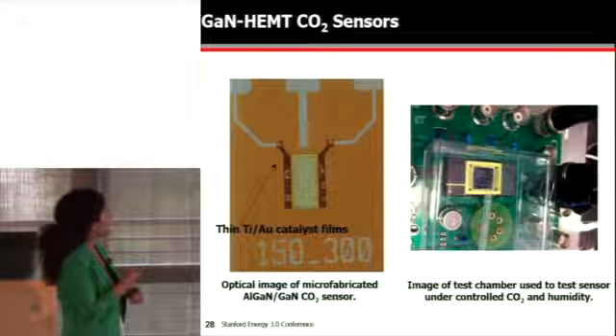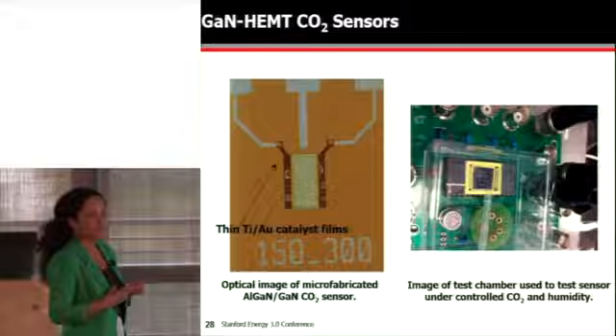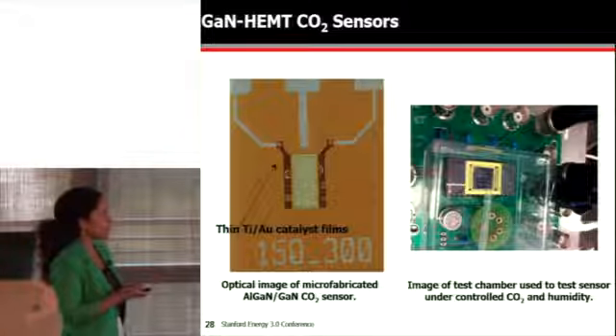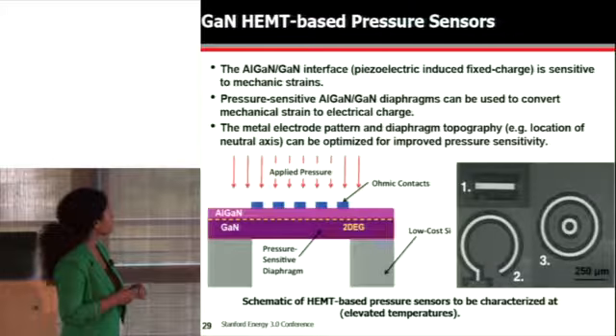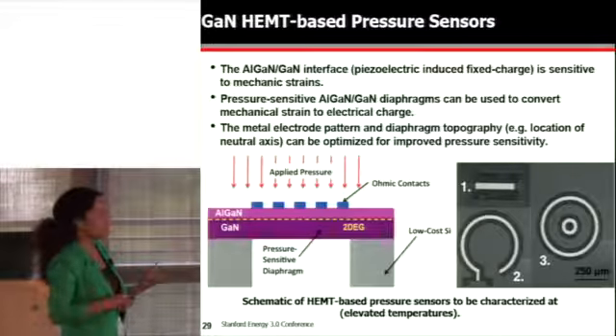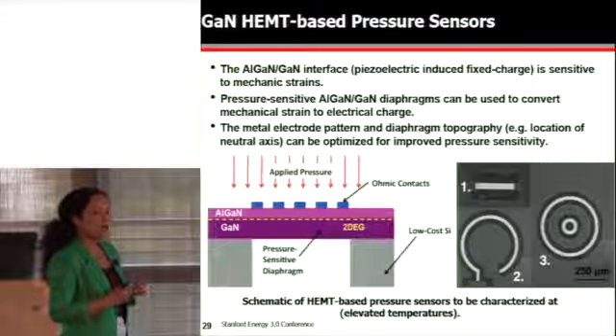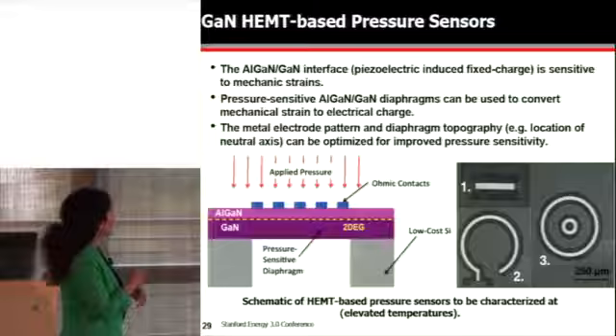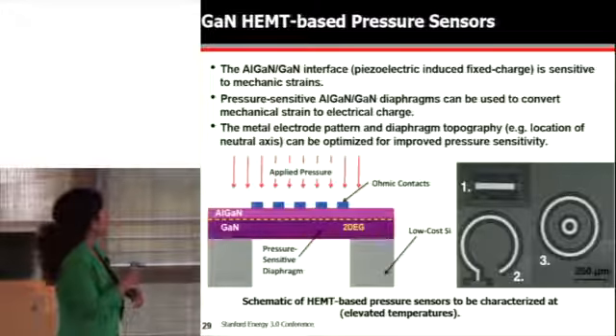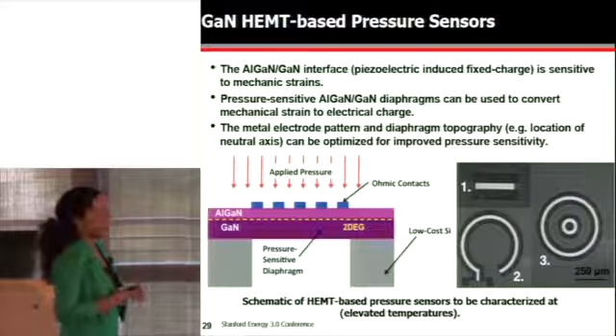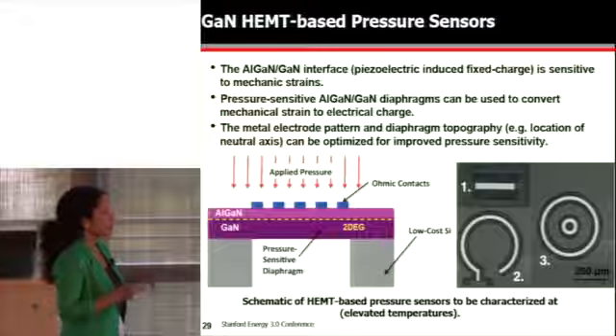And so the idea is that we can relate the concentration of CO2 to the IV characteristics of the sensor. In addition, we're creating high temperature pressure sensors. As I mentioned before, the gallium nitride is sensitive to applied strain. So if I create a diaphragm where I have applied pressure on top of it, the diaphragm will start to displace, and that will induce strain within the actual mechanical structure and change the strain profile on the transistors.